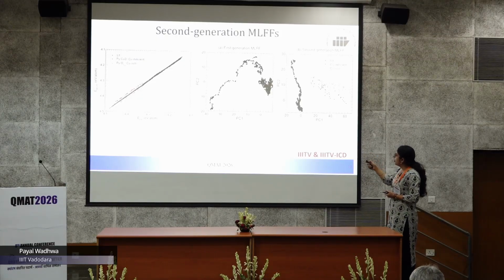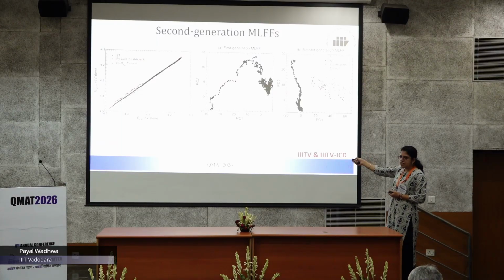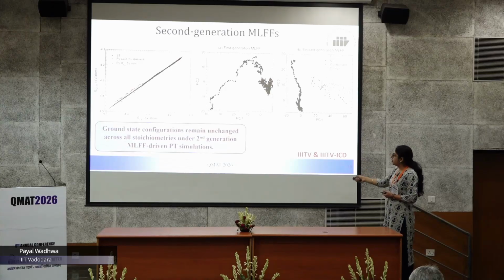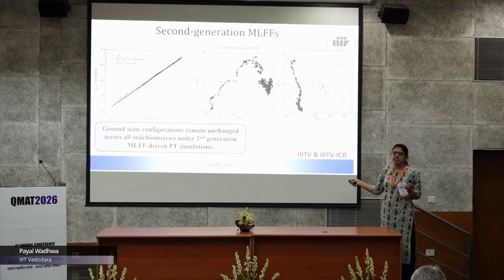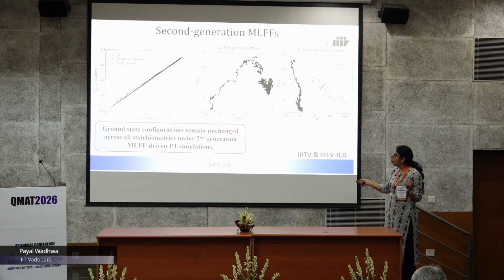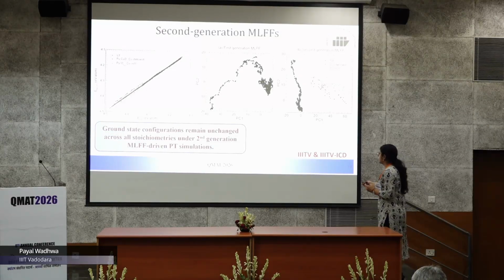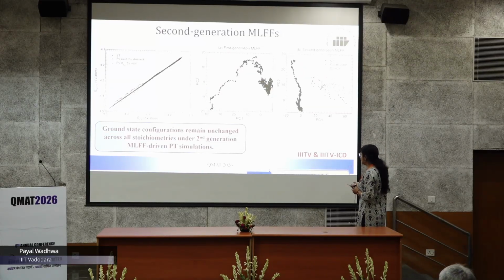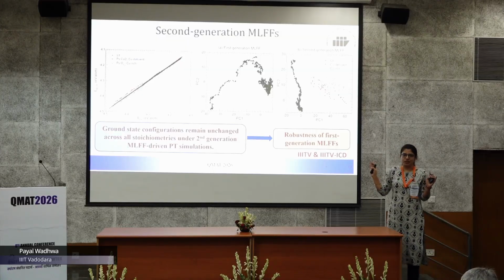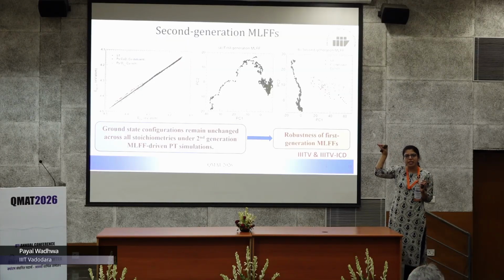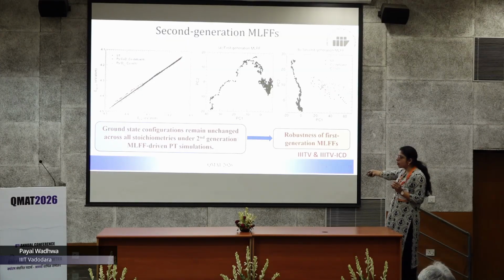And this clearly indicates that our machine learned force fields have diverse structures and contain a lot of distortions. When we perform PT simulations from the second generation as well, we found that ground state configurations remain unchanged for all the stoichiometries under second generation machine learned force field driven PT simulations. So it indicates that our original force fields, which we just took from the minimal configuration, are robust.